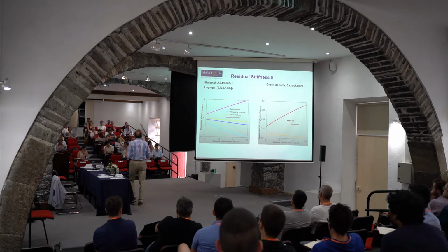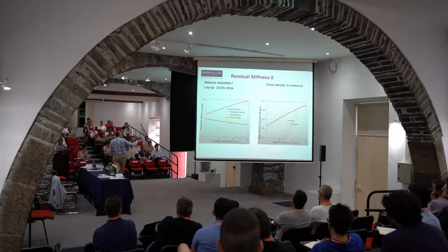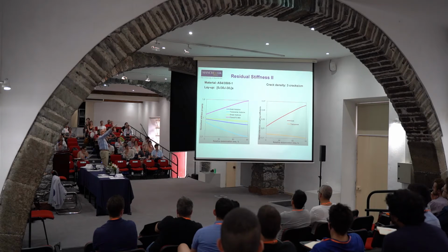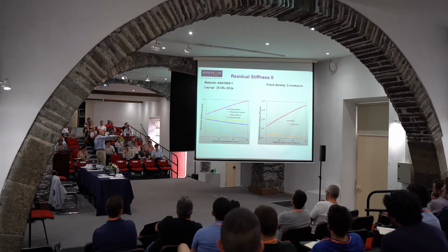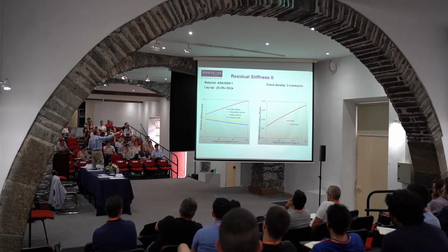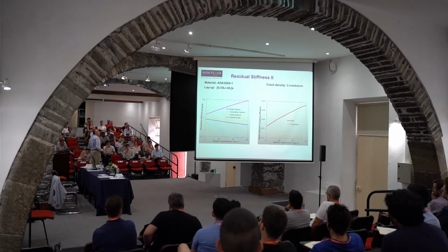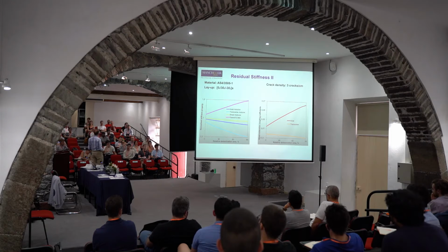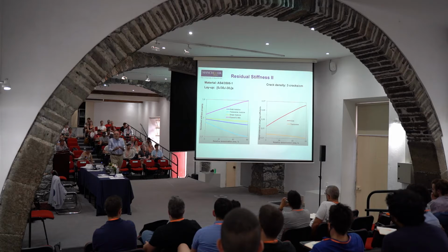And of course, now you have the effect of relative delamination area in an already cracked laminate where you have 3 cracks per centimeter crack density, and you can see the normalized stiffness property by how much is reduced, the axial modulus and the shear modulus. But the Poisson ratio is not reduced, it goes up. But you need to understand the physical meaning of the Poisson ratio.